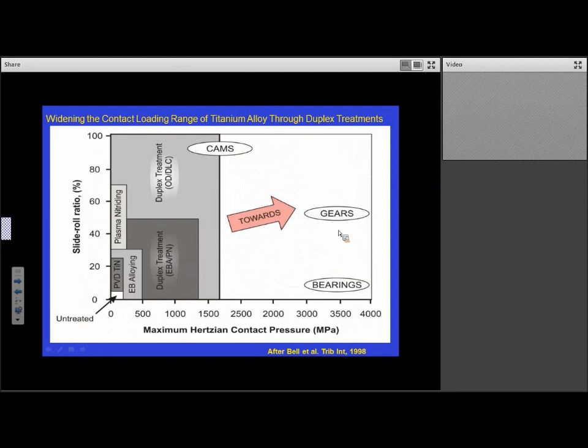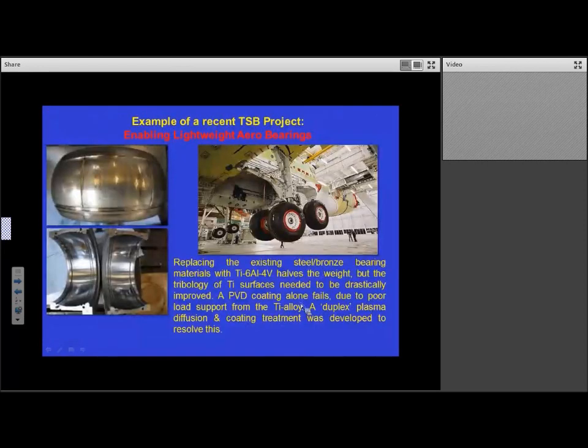We're now seeing bearings that can perform as well as or better than steel, and these were made of titanium alloys. And we worked on a project, again together with Warwick in Cambridge, TechVac and the bearing company, together with Adrian Leyland, my colleague, and we developed a pintle bearing, which was able to replace a steel bronze bearing in an Airbus undercarriage and take out hundreds of kilograms of weight.